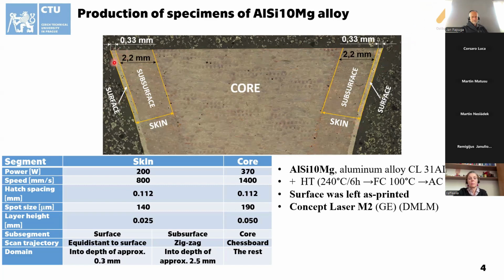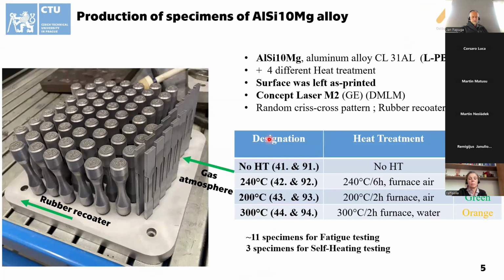There are, I hope it's visible on the screen, and it is part of the subsurface, which is printed with the parameters that we call the skin, or they call the skin, and this is printed in each layer. However, the core section is printed with double the layer height and nearly double the laser power. About the heat treatment, what we can see here is also mentioned the trajectory of the gas atmosphere and the rubber recoater. This is actually the first platform, the 41 to 44.